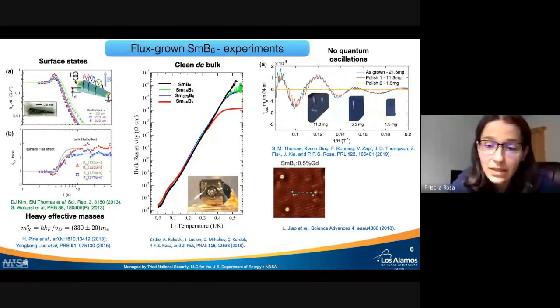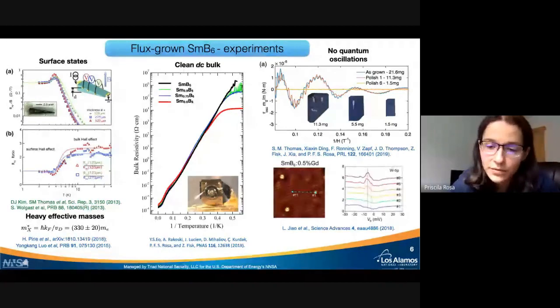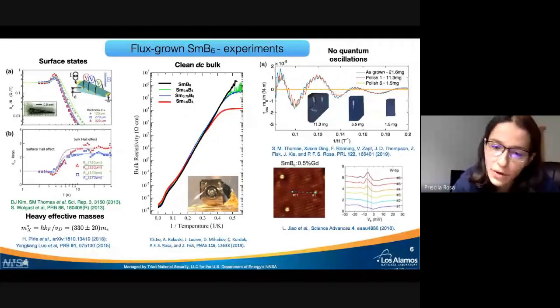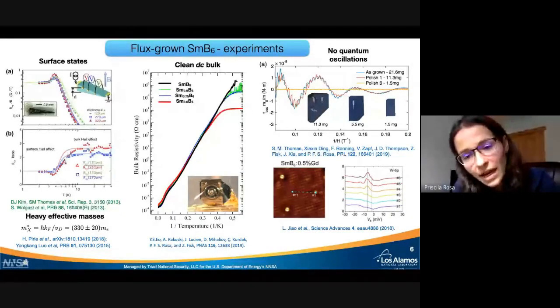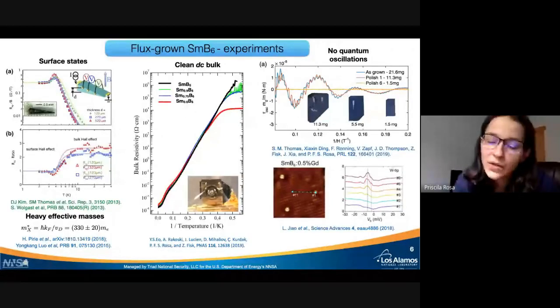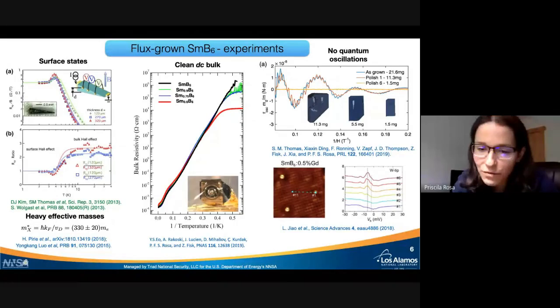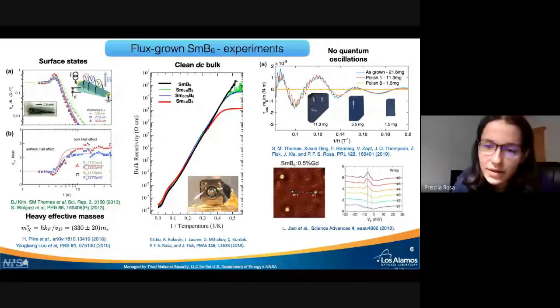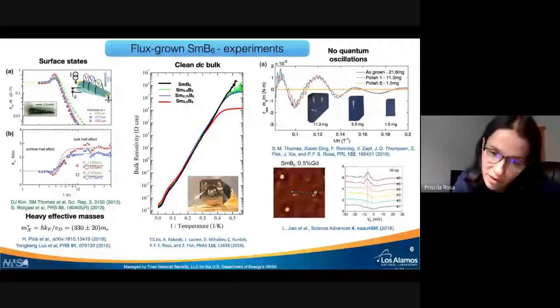And here we see dI/dV spectra at various points of the sample. So number one is when the tip is on top of the gadolinium impurity, and as you go up, you go away from the impurity. So you can see that number one doesn't have really anything showing up in a pronounced way. But as you go away from the impurity, a little bit of a peak starts to occur. And that peak is associated with the surface states of this material.